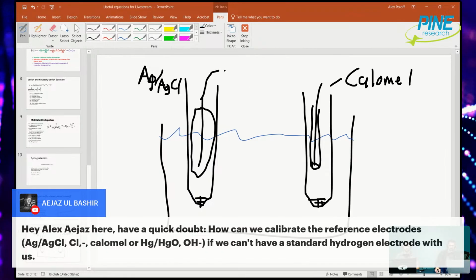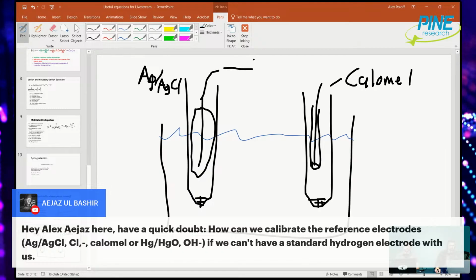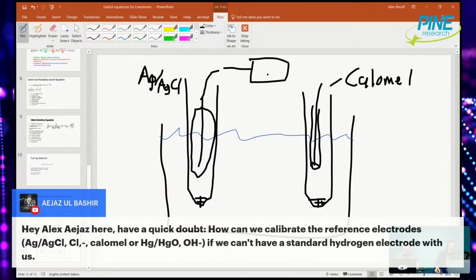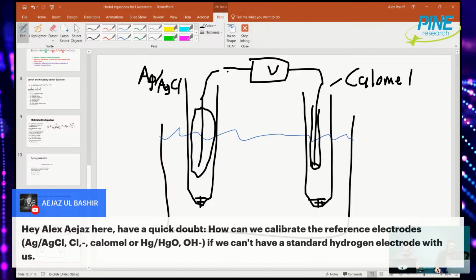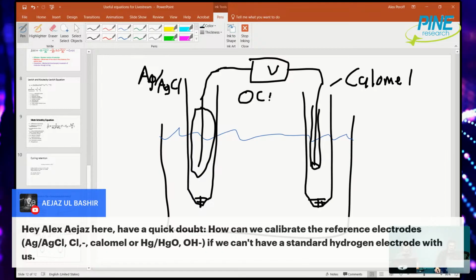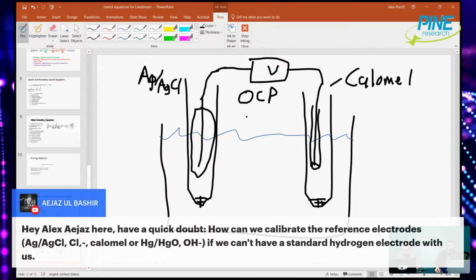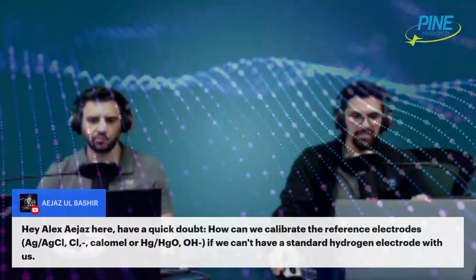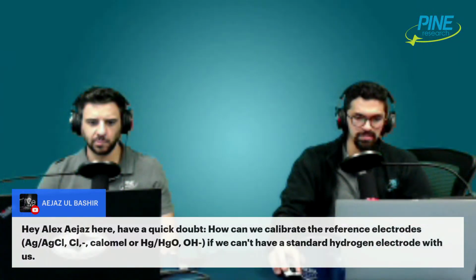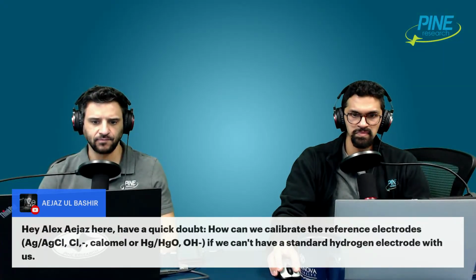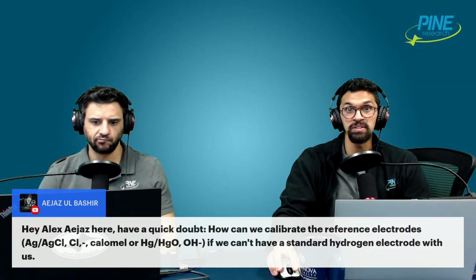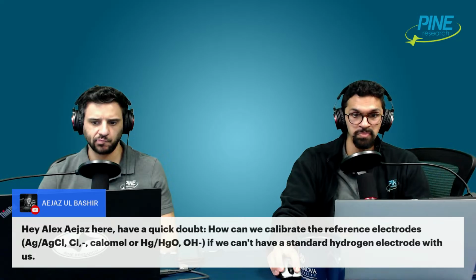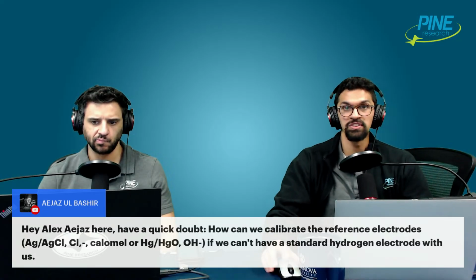And what you can do is measure the open circuit potential. Use a voltmeter and connect these two together. So you'd look at the OCP of this, and the OCP will measure the potential difference between these two. What you want to do is compare the OCP value that you get for those two pairs with that of the literature.